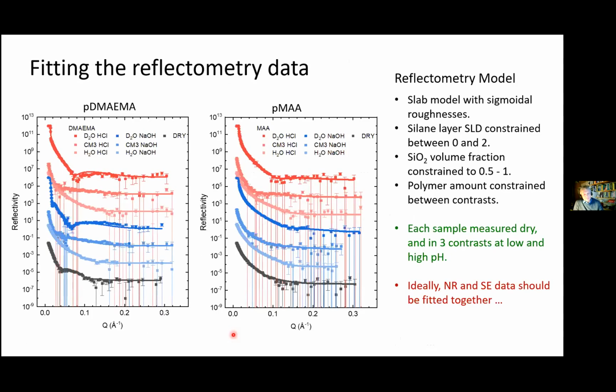So we've done fitting of the reflectometry data. We measured the cationic and anionic polymers in different contrasts, D2O, CM3, H2O, and also under dry conditions. So each sample was measured in 3 contrasts at low and high pH. The reflectometry model is fairly standard, I would say, for this type of system.